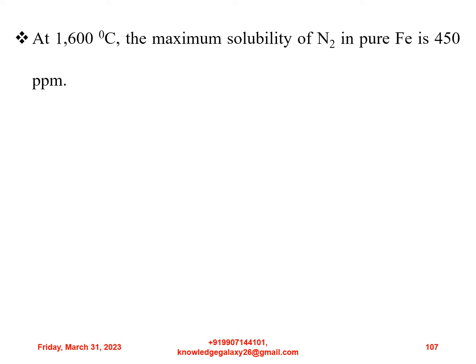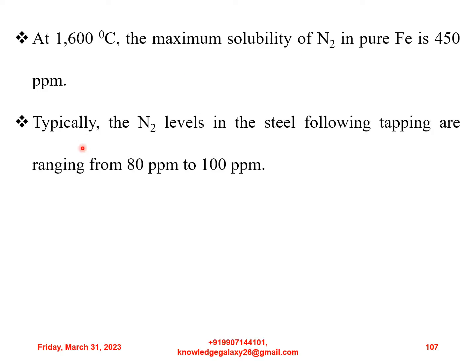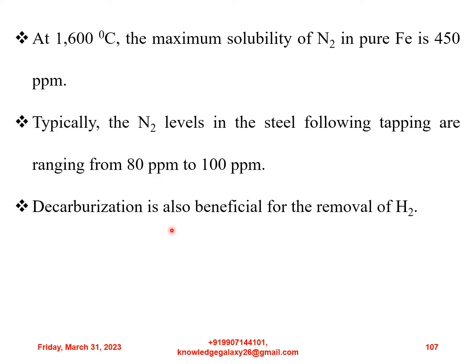At 1600 degrees Celsius, the maximum solubility of nitrogen in pure iron is 450 ppm. Typically, the nitrogen levels in the steel following tapping range from 80 ppm to 100 ppm. Decarburization is also beneficial for the removal of hydrogen. It has been demonstrated that decarburizing at a rate of 1% per hour can lower hydrogen levels in the steel from 8 ppm down to 2 ppm in 10 minutes.